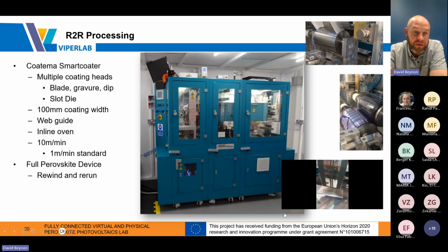And with this facility, we have produced full perovskite devices, all slot die coated, roll to roll. There's one coating head, but we put the substrate in and run through the first layer, so in our full device stack that is tin oxide. We'll rewind, then print the perovskite, follow that with PEDOT and complete it with a printed carbon electrode to have a fully coated perovskite device coming off at the end.